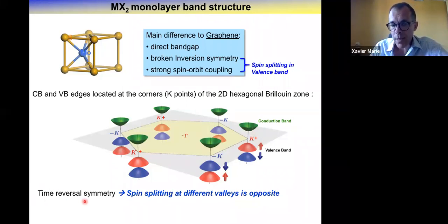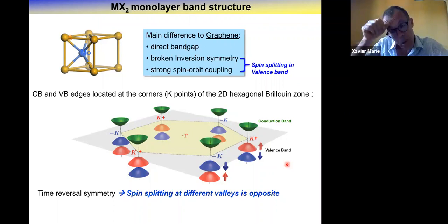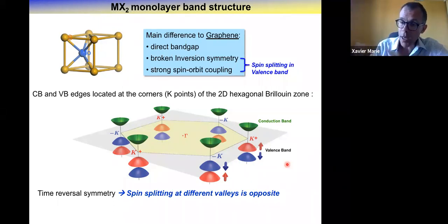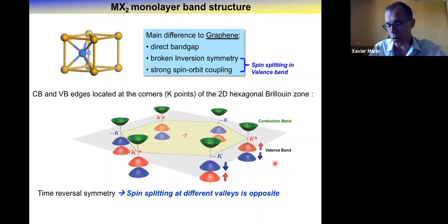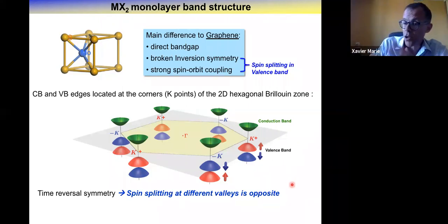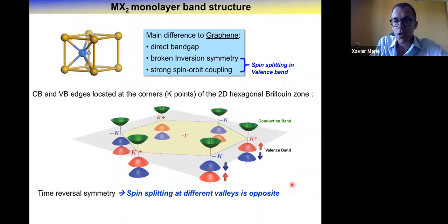And again, if you look at the symmetry, the two adjacent valleys, K plus and K minus, are linked by time reversal symmetry. So it tells you that the spin splitting in these two adjacent valleys is opposite. Here at the top of the valence band, you have spin down state. Here at the top of this valence band, you have spin up state. So this will yield very interesting and unique properties because you have a locking between spin and valley, and it has been described a lot in the literature. It will also yield very unique optical selection rules. I will not detail this today.